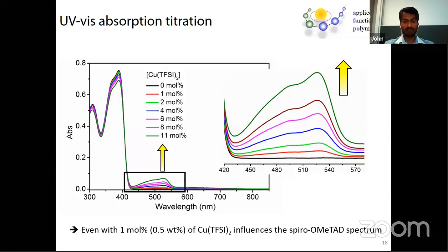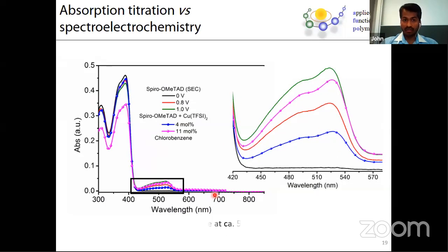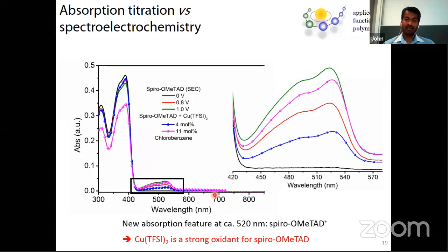Now if you compare the spectroelectrochemistry and the peaks that we obtain here, which I will show in the next slides, we see the new feature around 520 nanometer, which clearly tells that there is redox chemistry going on between copper TFSI and spiro-OMeTAD. So here is where we compare.